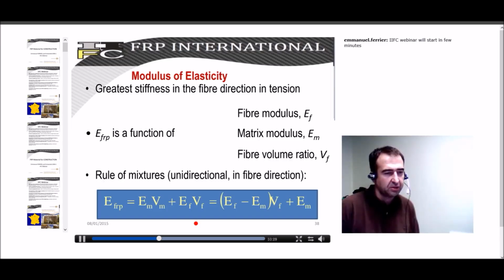About properties, as I mentioned first, the Young modulus can be easily calculated here using quite simple mixture properties. It means that your final properties will depend on the matrix properties and the fiber properties. If we compare the Young modulus of the matrix and the fibers, you can observe that even if we have 70% of the FRP that is made of matrix, the mechanical properties will essentially depend on this ratio, which is